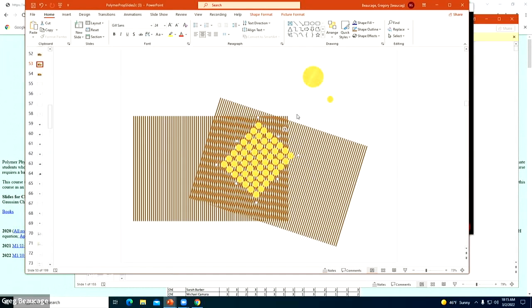The other thing you can do is, instead of monochromatic radiation, just let white radiation come in, any wavelength, and that broadens the window over which you can get this interference pattern. So not just one spacing, but all possible spacings within a reasonable range. Then you will get the pattern even from a perfect crystal. That technique is called the Laue method. You come in with white radiation.